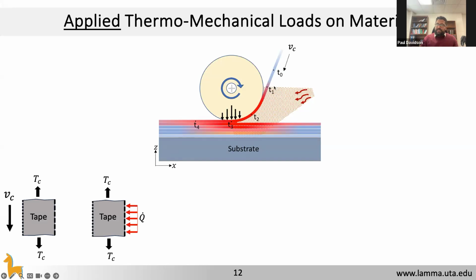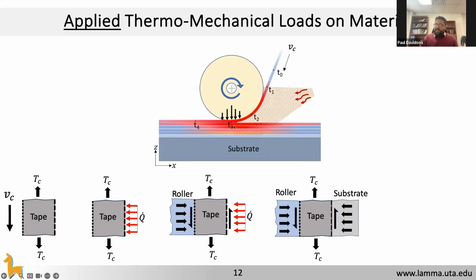As it goes through, you are heating the tape at T1 only on one side. So you apply some sort of flux, and then it attaches itself to the roller. It goes through the lower roller, which imparts one-sided compression, and then you have a bending. So the tension in the tape increases, and also you introduce shear. Then once it goes to T3, where you have the substrate, it comes under contact with the substrate. Now the tape is under compression, tension, and it is hot. That means it is trying to go through a thermal cycle. And finally, when it goes through cooling, the tape is crystallizing, and internal residual stresses develop and so on.